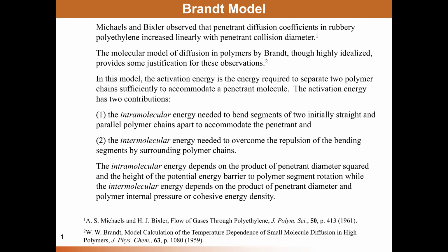And the reason I want to talk about it just a bit is because it captures a notion or an idea in diffusion phenomena that is not captured in the Mears model. So the Mears model is all about the activation energy of diffusion coming from breaking the cohesive bonds between the polymer segments to permit the creation of a gap that would turn out to be the activated state for diffusion.